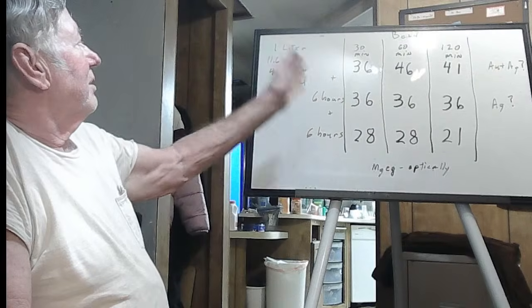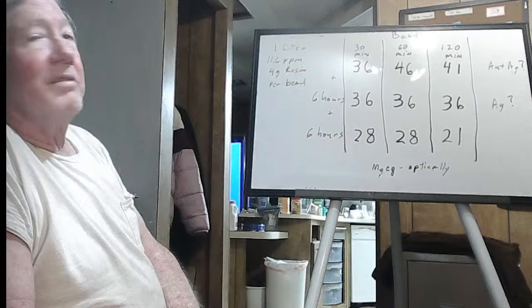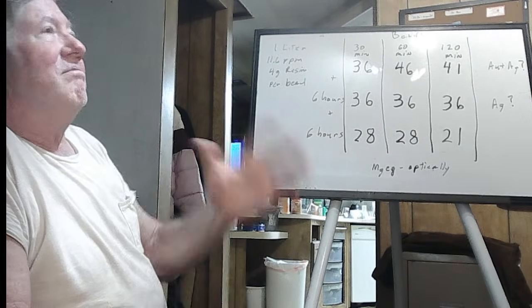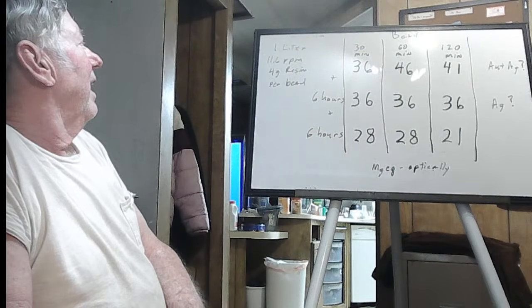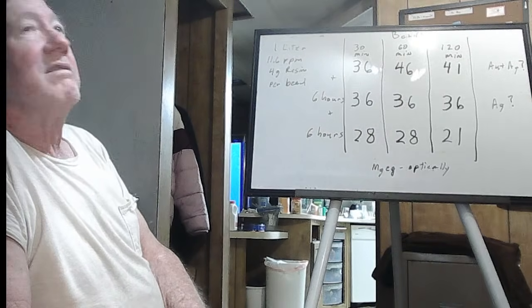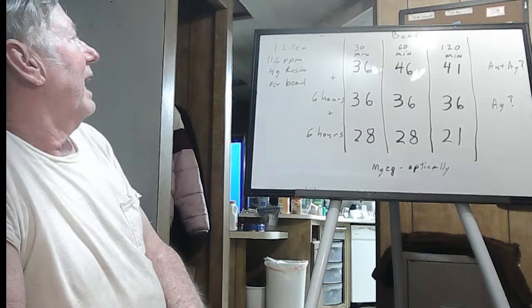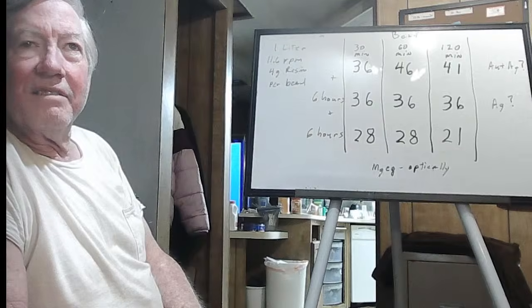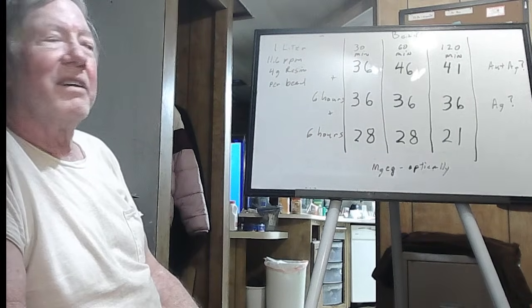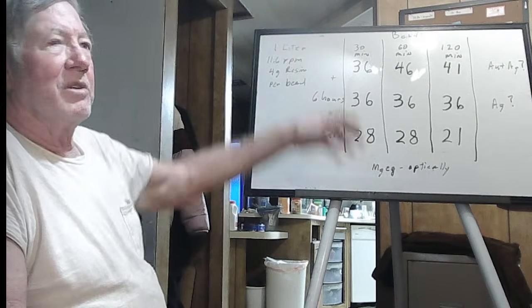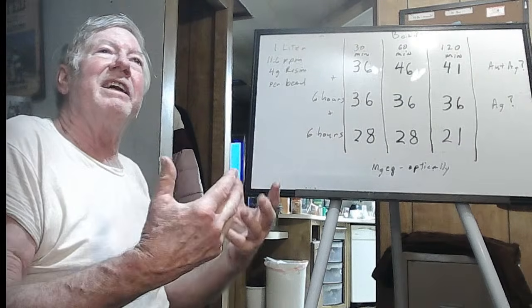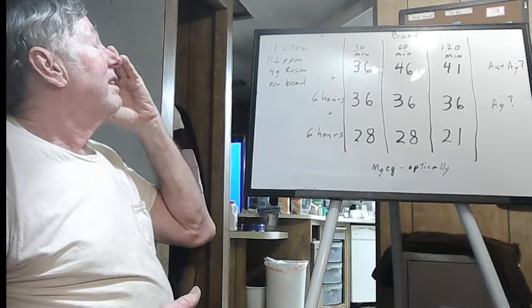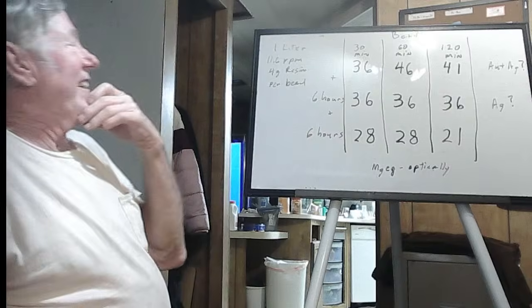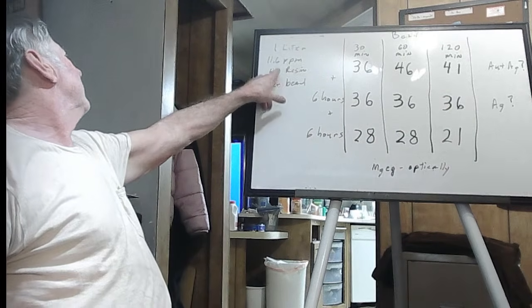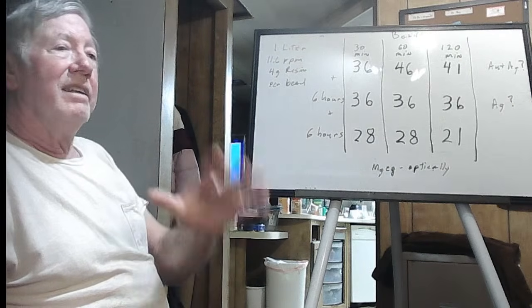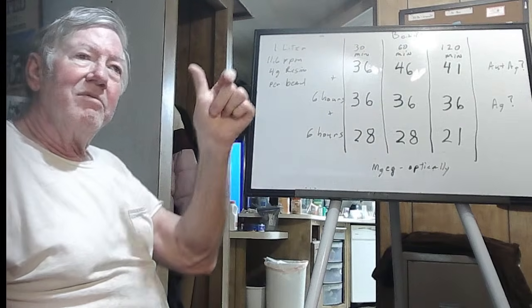So what I did was I took 3 1-liter samples of solution that I have handy, that fits reasonably well into one of the bottles that I use. And I put 4 grams of Maxwater resin in each one, knowing that that was an abundant amount of resin to absorb that gold. The amount of gold in the bottle would easily absorb onto that much resin. The idea being I'm trying to test speed, not loading factor. So each one of these columns is 1 liter of solution at 11.6 parts per million. Fairly low concentration, lots of resin, should go quick.